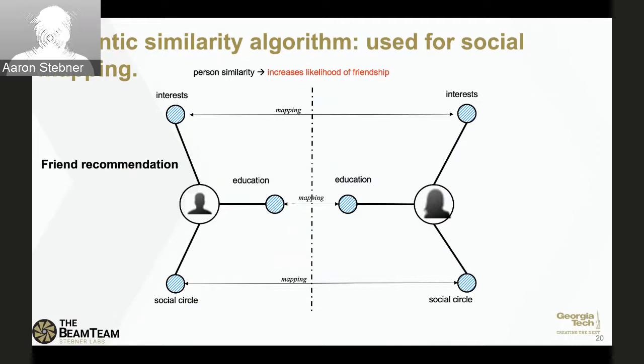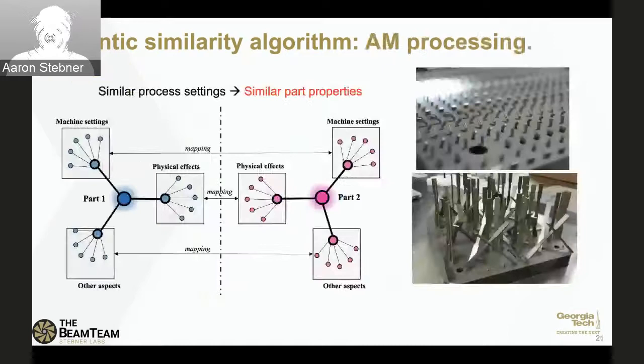If you go to the next slide, for additive manufacturing, we were able to look at similar machine settings, similar other aspects here, which may be porosity or strength or those outputs. But then these calculated physical effects like recoil pressure, number of layers, laser spot size, et cetera, were also part of that mapping. And when we did this augmented similarity mapping, if you go to the next slide,